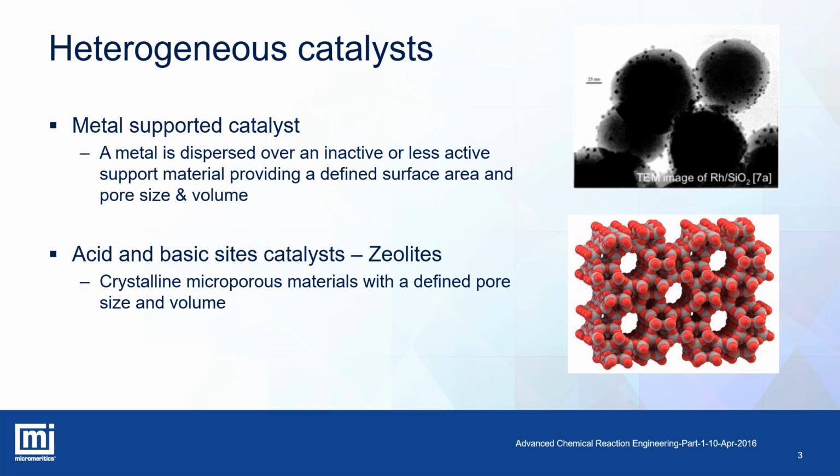Zeolites are crystalline microporous materials forming frameworks with up to 3-dimension pore networks ranging from 0.3 nanometer to about 1 nanometer size. Metal ions, silicon and aluminum, are linked through oxygen or hydroxyl bridges, generating acid sites on the internal surface. Bronsted acidity is mainly related to the ratio between silicon and aluminum, while the introduction of other cationic species like transition metal ions may provide the zeolites with the Lewis acid sites or redox catalytic properties.